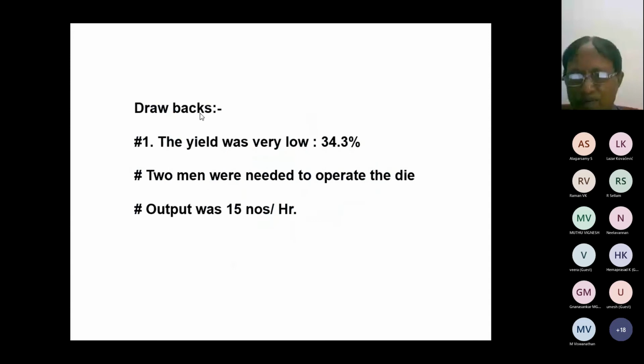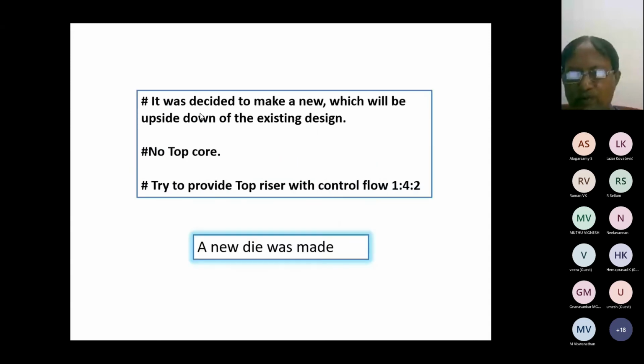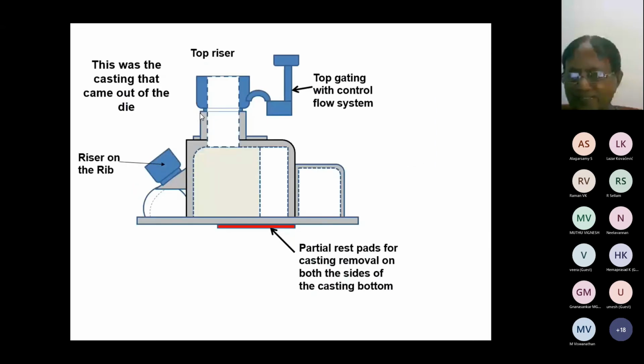So one bold approach was made. Why don't we make the die upside down like this? This is the die. This is the casting. These two are joined as one bottom core. I didn't make the right drawing. And this is the top riser again as ever. We go for top pouring with a 1:4:2 ratio and try to fill the casting. For the rib portion, we have provided a bulb riser to hold these ones. And to hold the casting on the base, we have provided this one because the core profile was totally different. It's a triangle. And these two pairs serve as a resting point for the casting when the core drops down.